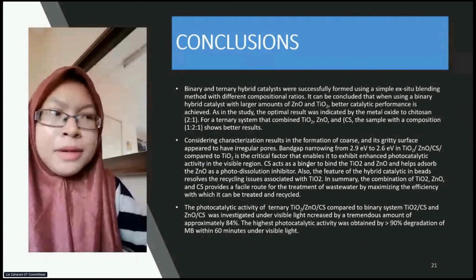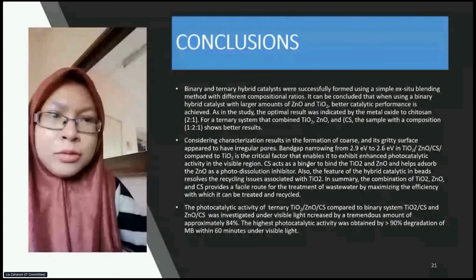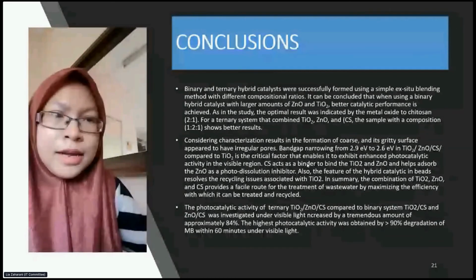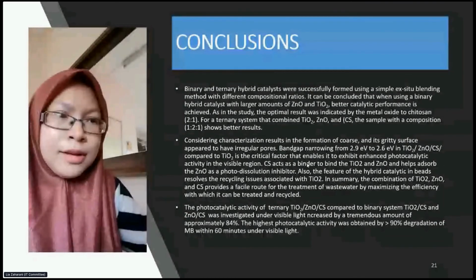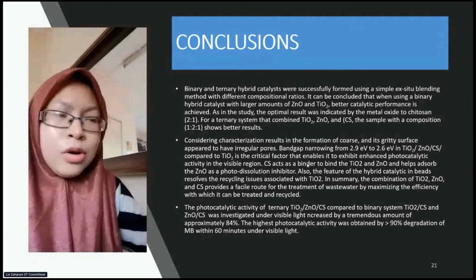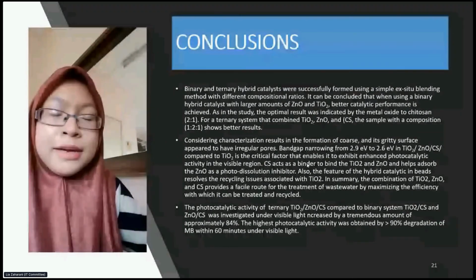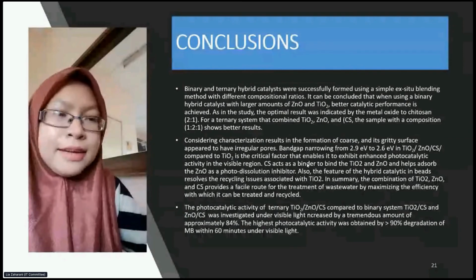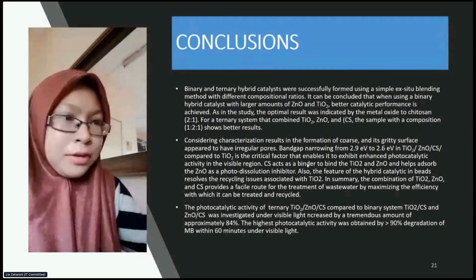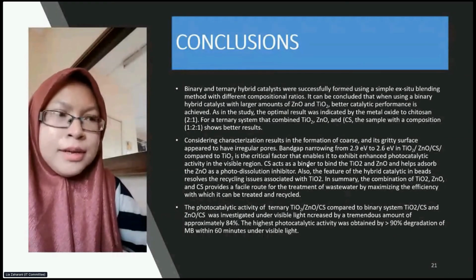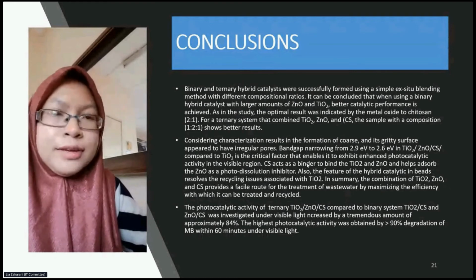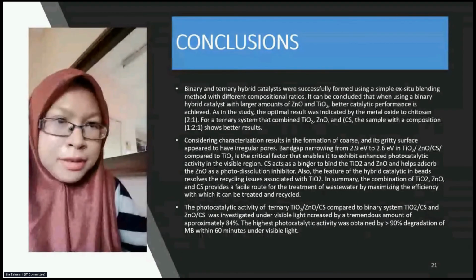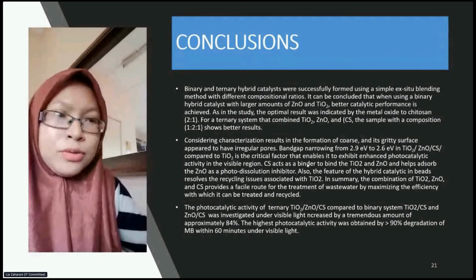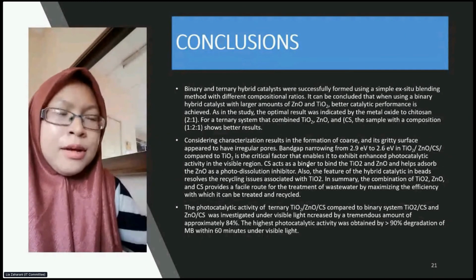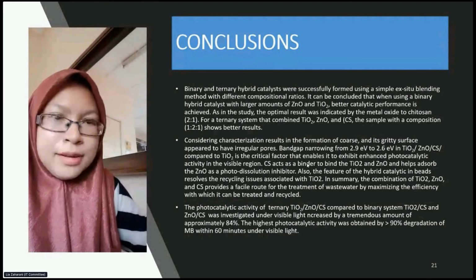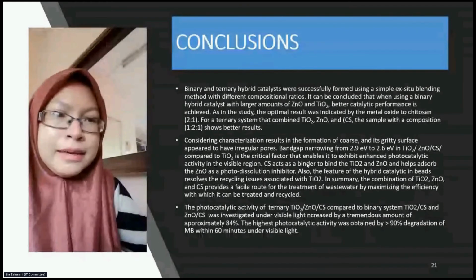Chitosan acts as a binder to bind the TiO2 and zinc oxide and assists the absorption of the zinc oxide as the photodissolution inhibitor. Also, the further use of the hybrid catalyst helps resolve the recycling issues that have been associated with the TiO2 system. In summary, the combination of these three elements provides a facile route for water treatment by maximizing the efficiency, as it can be retrieved and recycled.